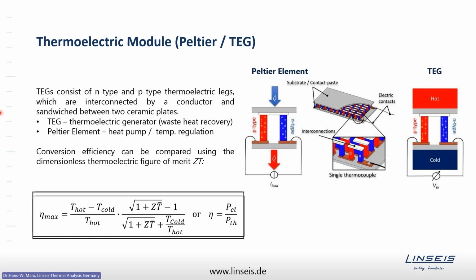Once you found a good thermoelectric material, in order to make use of it, so-called thermoelectric modules or thermoelectric generators are built up. In these generators, you combine P and N type thermoelectric materials. Put them either between a hot and a cold side and harvest the voltage. This is a thermoelectric generator, or you may use it as a Peltier element by powering it by an electrical current and get a temperature gradient, so meaning a cold side and a hot side.